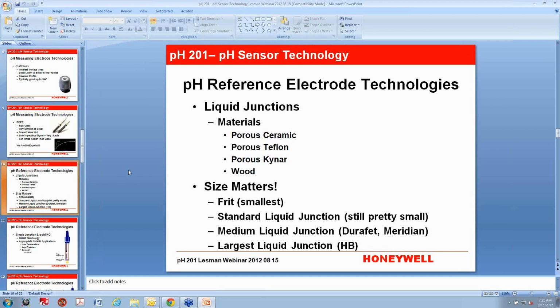They tend to get plugged up. Wood makes a good liquid junction, but it is susceptible to chemical attack a lot of times, so you have to be careful where you put that. So my vote is for an overall material. I like porous Teflon, followed closely by porous ceramic. And with the liquid junctions, the size of those holes or the pores is very, very important, and the size